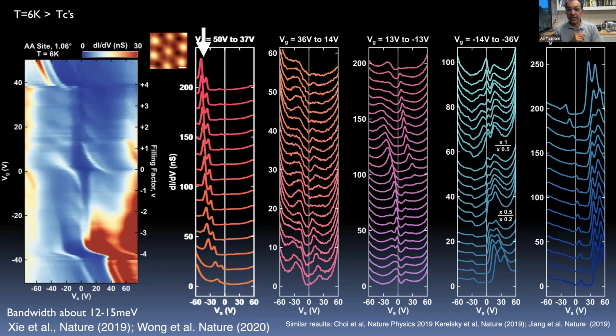So our first discovery in this field was that when you partially occupy the band, the spectral property of this material goes from very sharply well-defined Van Hove singularities to extremely broad spectral weight. And this is something that in hindsight we understood, but at the beginning, no experiment like this was ever done before in such a strongly correlated system, where you tune the system from being non-interacting, which is when the bands are completely full or completely empty, where you have these sharp peaks, well-defined quasi-particle, single-particle physics explains the property of the system, to what you have in the middle.